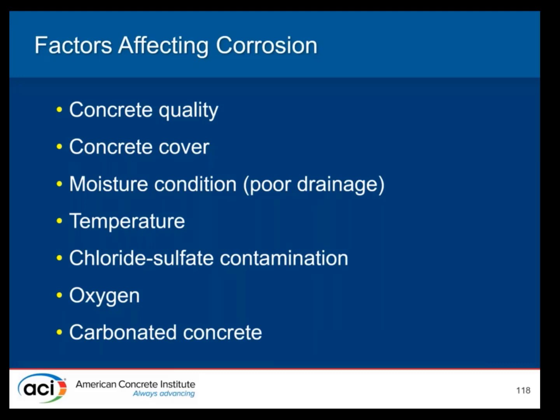Temperature. Obviously, being a chemical reaction, the higher the ambient temperature, the higher the rate of corrosion. A combination of chlorides and sulfates can get together and cause even more damage, where you have the chlorides attacking the reinforcing steel and the sulfates attacking the cement. Oxygen needs to be present, for most cases. There are situations where corrosion can occur in low oxygen environments, and that's a little bit more complicated, and we're not going to talk about that today.